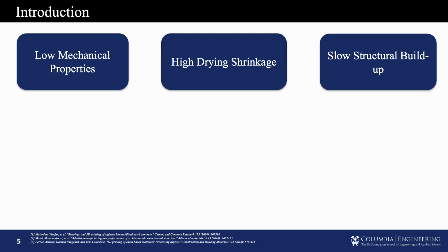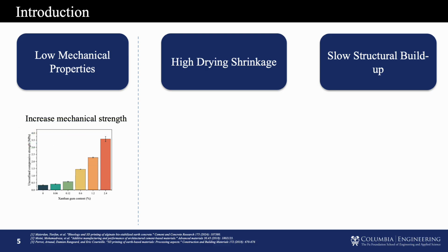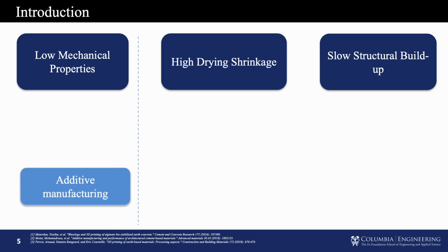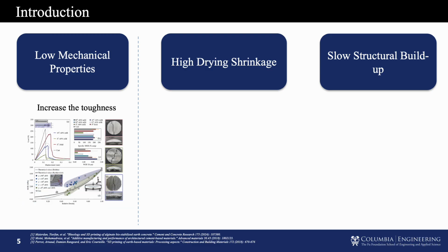In addition, we also have a slow structural buildup rate because of the slow dehydration or drying process of the earth-based material. In this work, we try to use biopolymers and additive manufacturing technology to solve these three challenges. First, bio-based material like biopolymers can be used as a binder, which can increase the compressive strength of the material. I believe Bex's work already showed this very well. And in addition, additive manufacturing technology, although it cannot directly increase the compressive strength, with the architectural design of the material pathway, can increase the toughness of the printed structure.